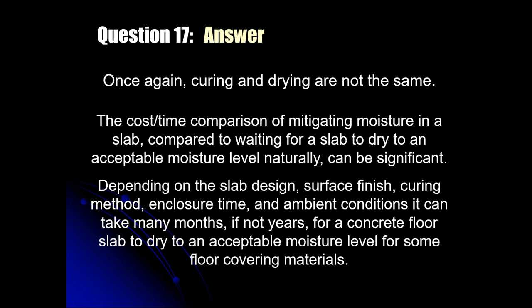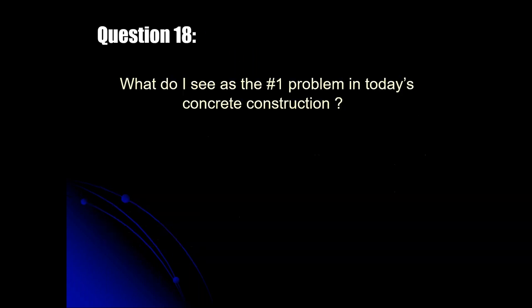It can be significant. It really can, because depending on the slab design, the surface finish, the curing method, and closure time, it can take many months, if not more than a year, for a concrete slab to dry to an acceptable level. And if you haven't made the decision ahead of time to mitigate moisture and take the opportunity to do so early in the construction process, if you wait until what I call the 23rd hour, you're framed, you're sheetrocked, you've got 6 or 8 other trades in the building trying to work at the same time, and now you have to implement a moisture mitigation strategy, it becomes a much more difficult situation.